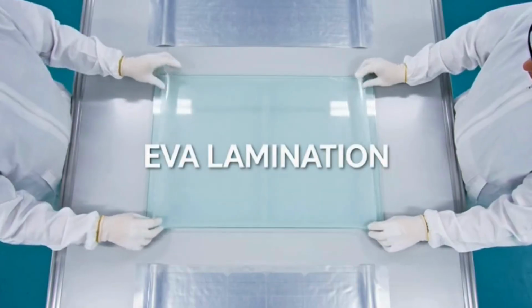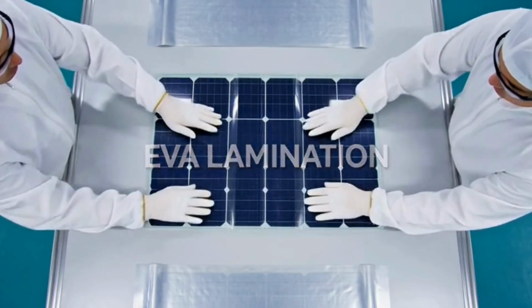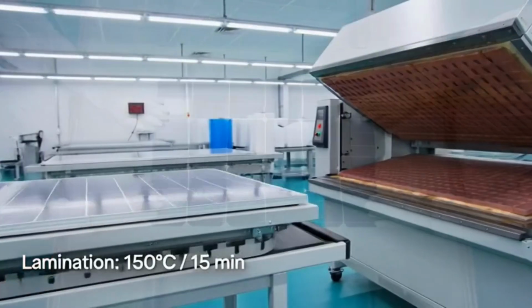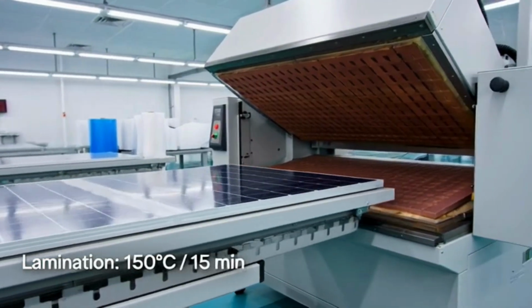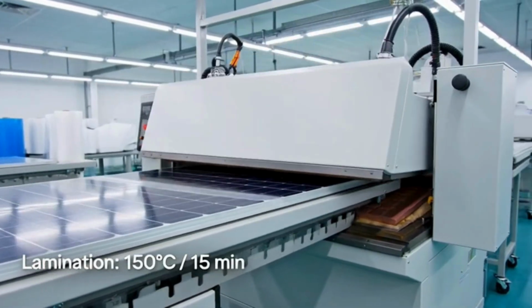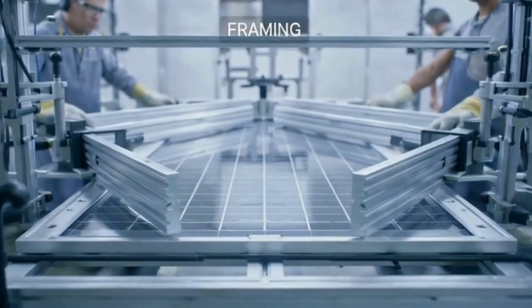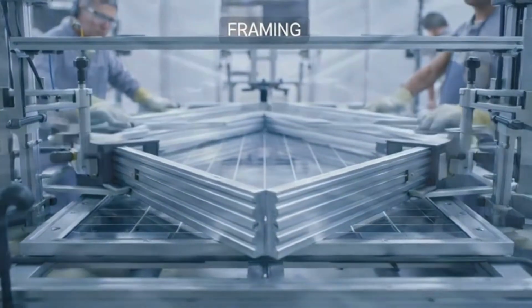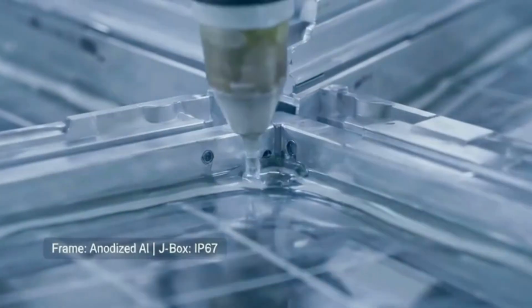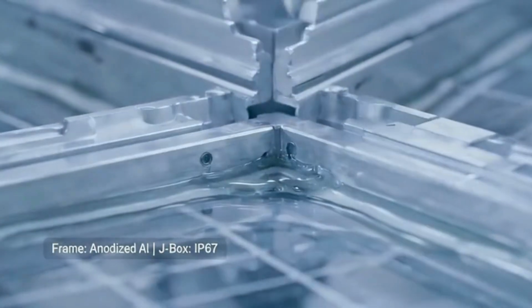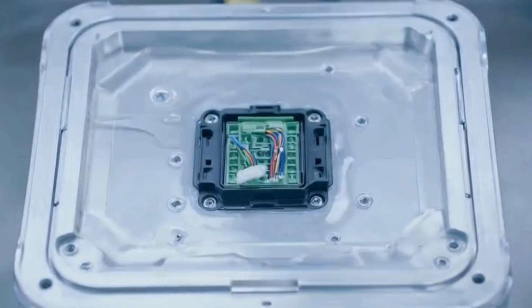Cell strings are layered between glass and backsheet, with EVA encapsulant film between each layer. A vacuum laminator seals the entire stack at 150 degrees, bonding it into a single weatherproof unit. An anodized aluminum frame is pressed onto all 4 edges and sealed with silicone. A weatherproof junction box, with bypass diodes, is bonded to the rear surface.